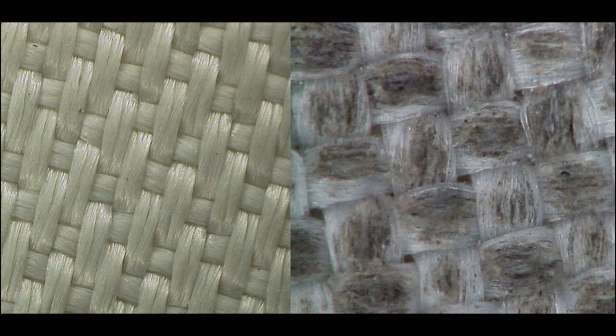Teflon is added to the silica fiber material by first coating the silica with a primer and then implanting solid PTFE particles in the primer layer while the layer is still somewhat tacky and able to trap the particles. The implanted particles then serve as anchor points for more layers of PTFE particles to be attached through the sintering at temperatures between 350 and 400 degrees Celsius.